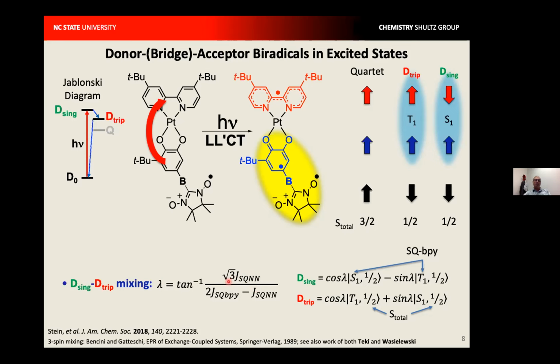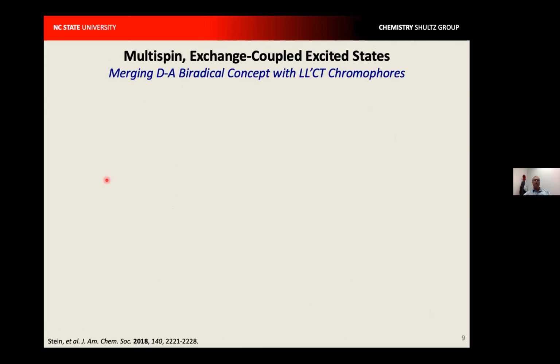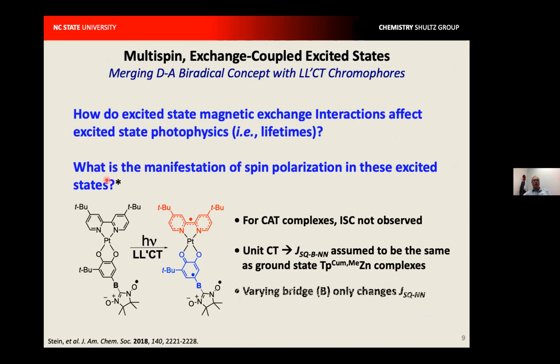So since the bridge controls this J, and since we equate this exchange coupling with the corresponding exchange couplings in the zinc complex, we can essentially determine the mixing parameter for D-sing and D-trip by changing the bridge and calculating what lambda would be. So we can essentially synthetically manipulate the energy gaps in this excited state manifold by changing the bridge in these complexes. And so to summarize, we get ligand-to-ligand charge transfer to make 3 unpaired electrons. We know the two major exchange coupling parameters in those excited states, and we can vary the mixing between the two doublet excited states by changing the bridge fragment in these molecules.